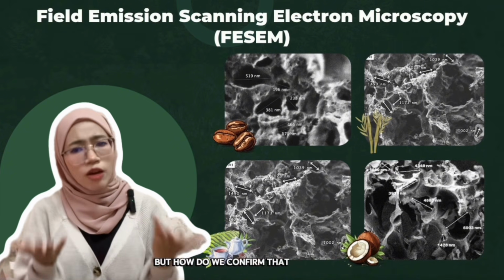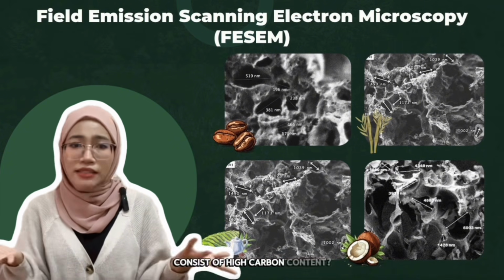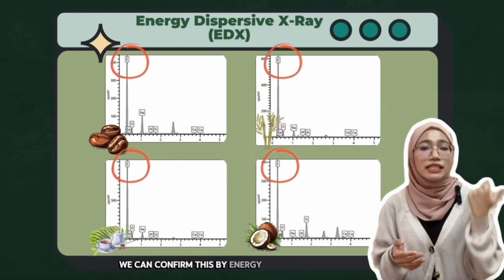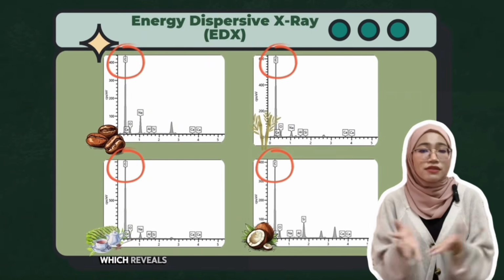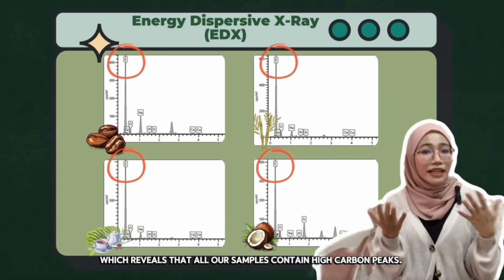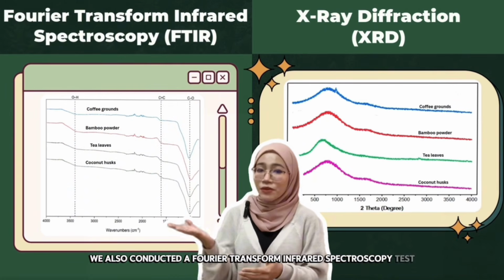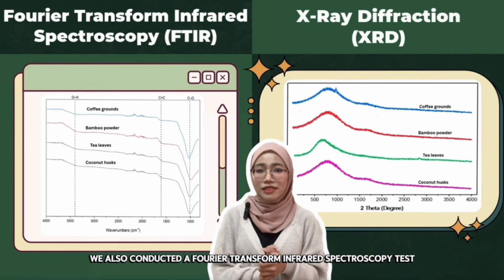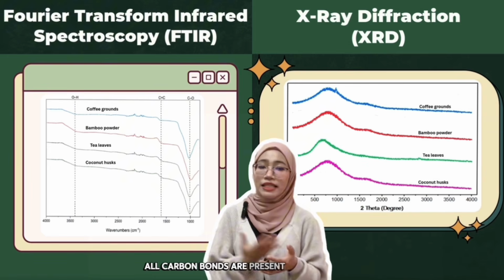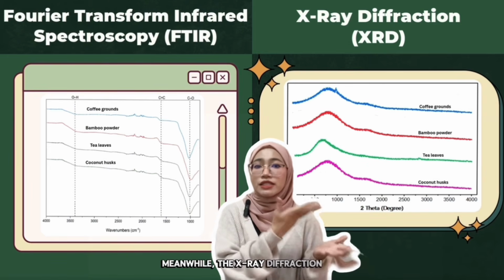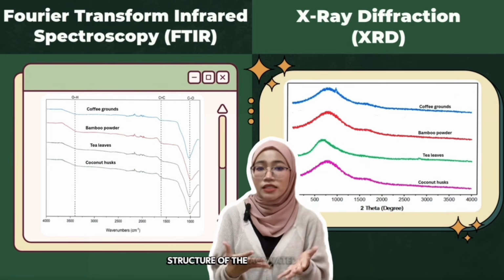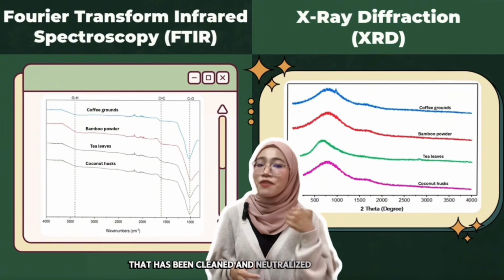But how do we confirm that our samples consist of high carbon content? We can confirm this by energy dispersive X-ray analysis, which reveals that all our samples contain high carbon peaks. We also conducted a Fourier transform infrared spectroscopy test to verify that all carbon bonds are present in the samples. Meanwhile, the X-ray diffraction test confirms the amorphous structure of the activated carbon that has been cleaned and neutralized thoroughly.